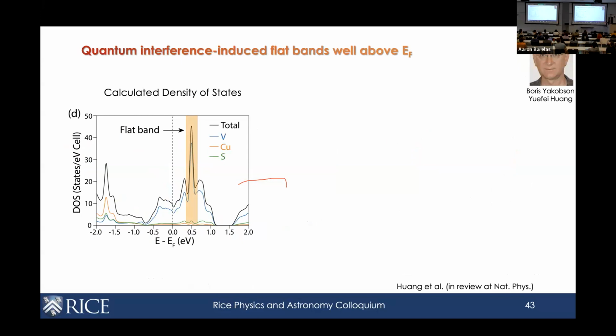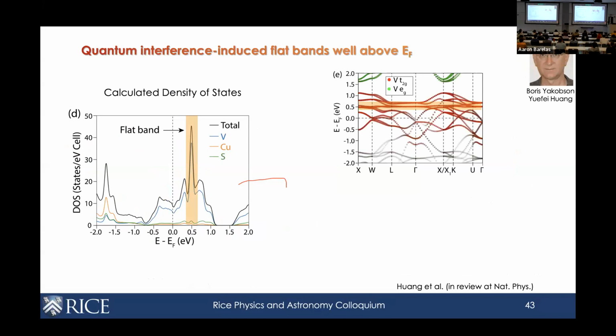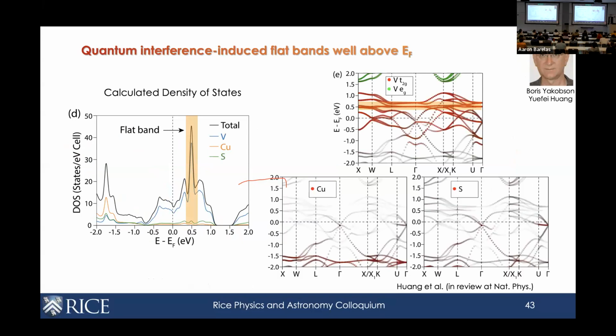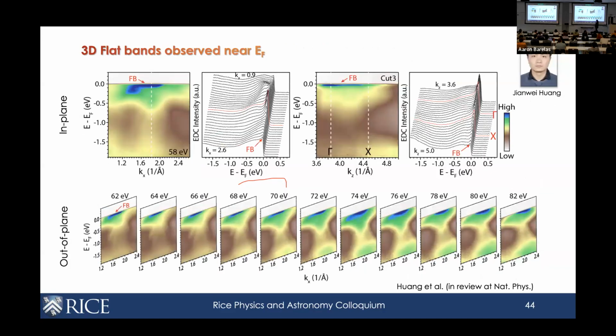And you can see the large peak, which indicates the flat band. And when they do the DFT calculation, they can indeed see this very flat band. What's more, if you do the projections to different orbitals, this is all coming from vanadium t2g, and copper and sulfur have very little weight near the Fermi level. This is also great, which means that we can think about the system as basically a pyrochlore material.